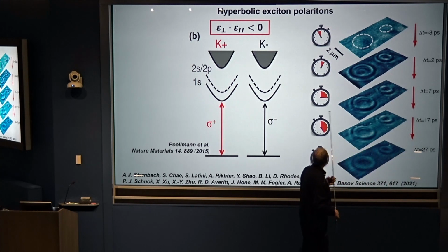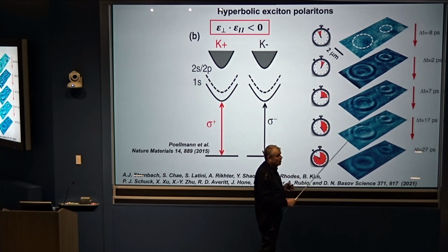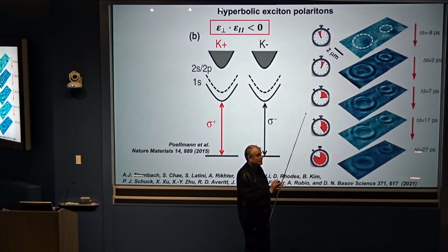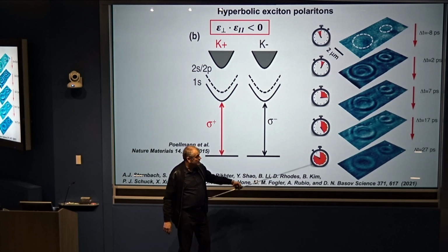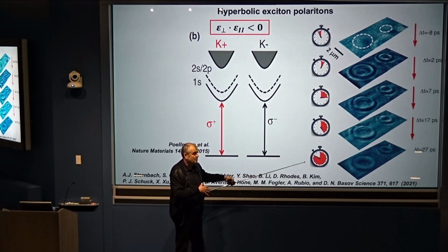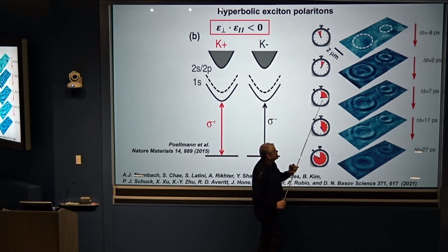So the pump is maybe 150 femtoseconds long. So it's an order of magnitude or more shorter than this lifetime. So it's definitely the relaxation is governed not by the pump but by physical processes in the material.